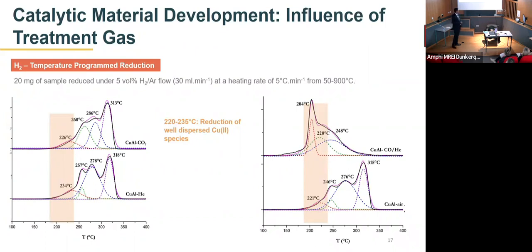low hydrogen reduction peak is generally associated with the reduction of well-dispersed copper-2 species. If we have a close look at the carbon monoxide treated sample, we also get a peak of reduction at 204 degrees Celsius. This could be because the metallic copper, when it was transported from the treatment to the TPR analysis, could have been oxidized by the oxygen present in the ambient atmosphere, and these species are now reduced at a lower temperature.